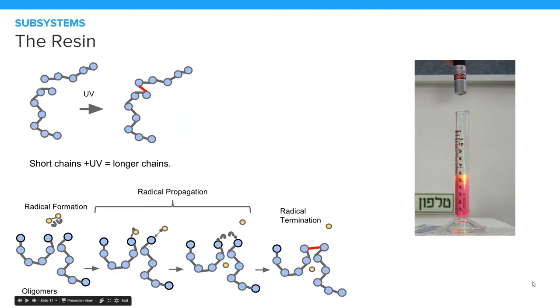In addition to the oligomers, monomers, and photoinitiators, the resin might also contain visual and/or functional additives like color and castability enhancements. In a little more detail, resin is a plastic composed of those molecule chains, and it has all the final properties of the final plastic, but it has not been fully polymerized or cured. Once an SLA resin is cured via UV light, it's chemically bonded, and that's why photopolymers are considered to be thermoset plastics. That means that once they're cured, the matrix is irreparably changed.